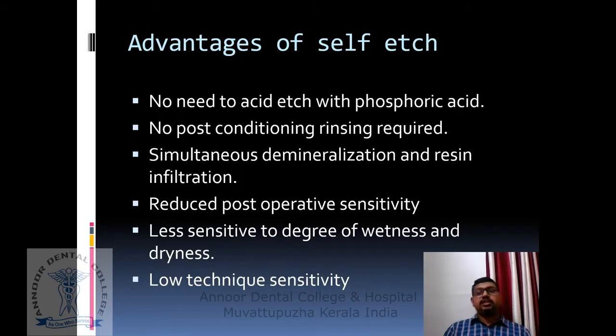Why reduced post-operative sensitivity? Suppose you are using an etch and rinse system. When you are using an etch and rinse system, the acid may have penetrated to a depth of 20 microns. When you dry the dentin and apply your bonding agent, the primer and the bonding agent might go in only 15 microns. So there will be 5 microns of demineralized dentin with exposed collagen that has not been infiltrated by your resin material. So there can be water movement in that layer. There can be sensitivity. That's why self-etch systems are better, because there is simultaneous demineralization and resin infiltration.